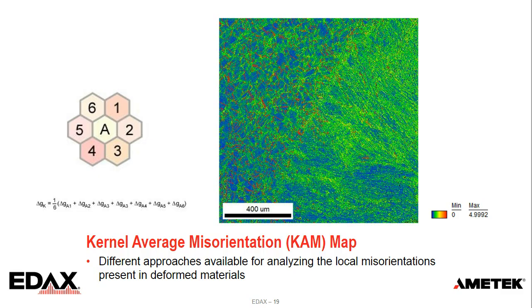So the color scale used here, blue is basically a 0 misorientation. Red would be essentially 5 degrees, and we often use 5 as a cutoff. After 5, it starts to be more of a higher angle, maybe a grain boundary. We can see in this map the weld area has a higher KAM value. It's a little brighter in the top right than on the base metal to the left, but there's still a good deal of KAM strength throughout the microstructure.